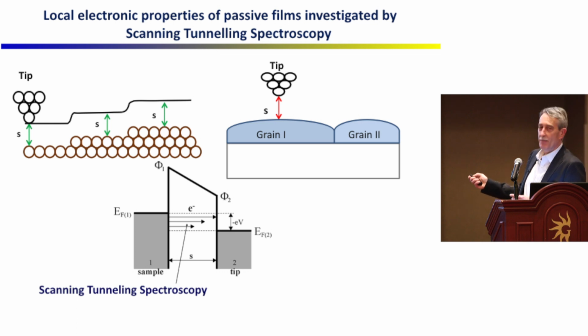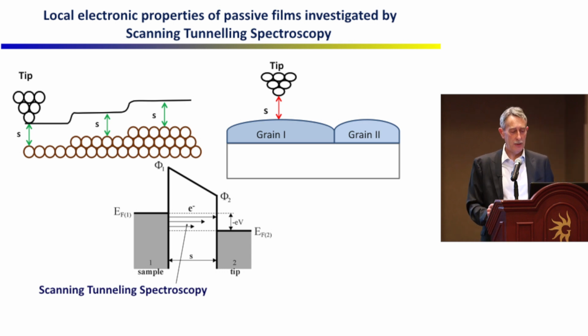But of course, we have many, many grains. The grains are not that big. They grow with potential, they grow with time, but they remain fairly small. So we have, of course, grain boundaries between these oxide grains. So we wanted to know whether we have a different electronic structure at the grain boundary.